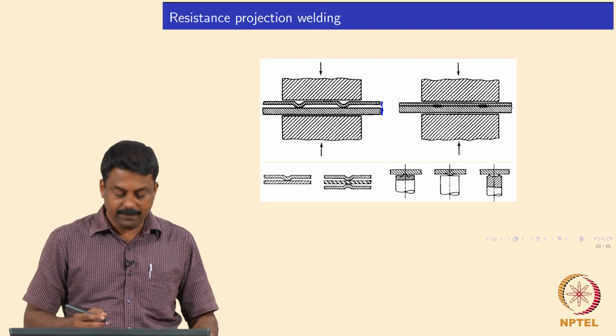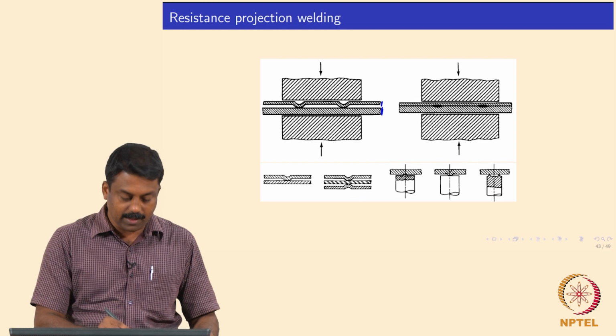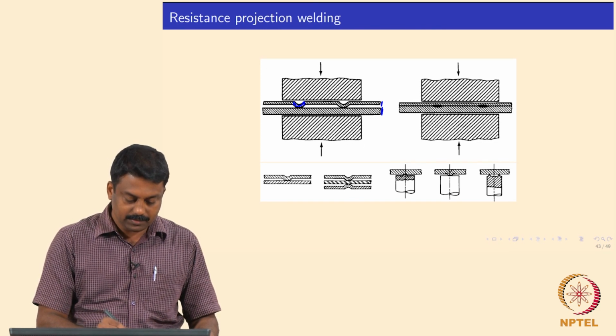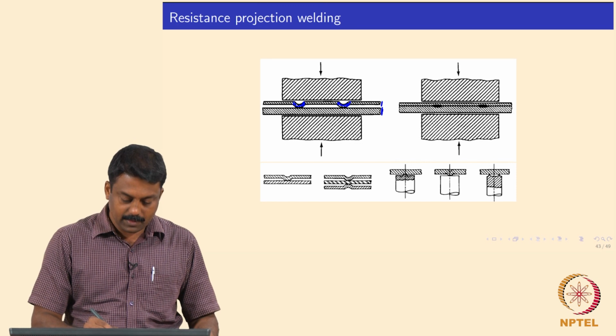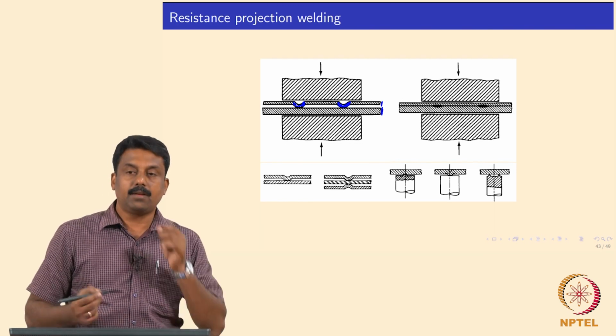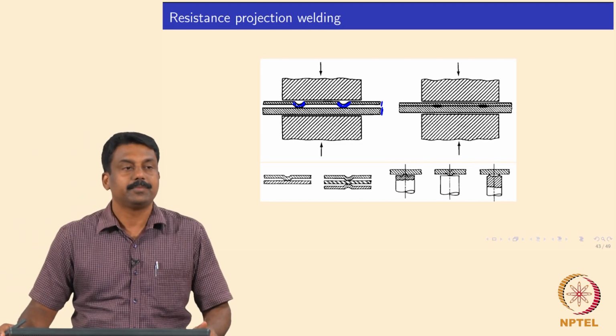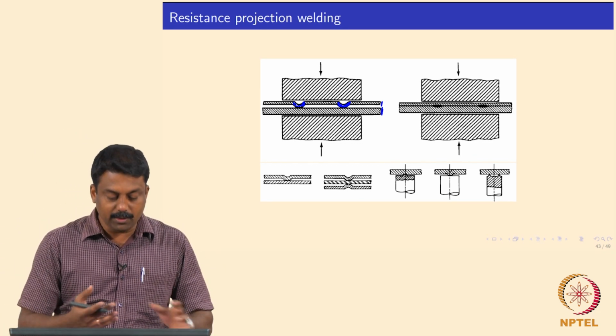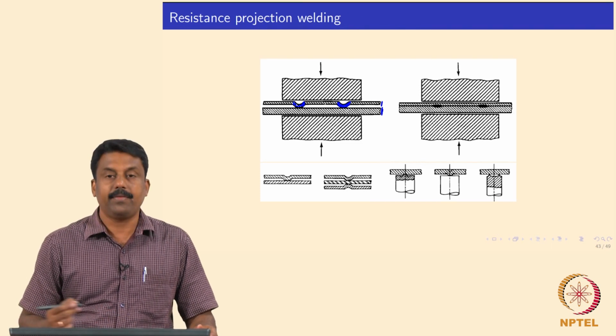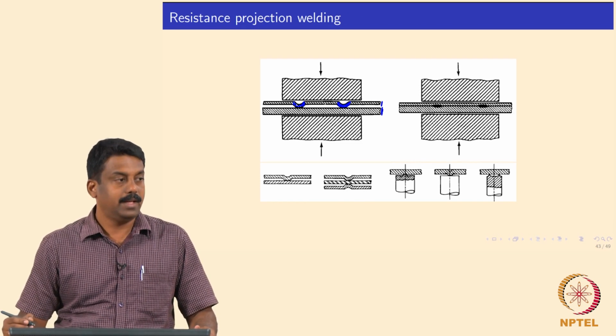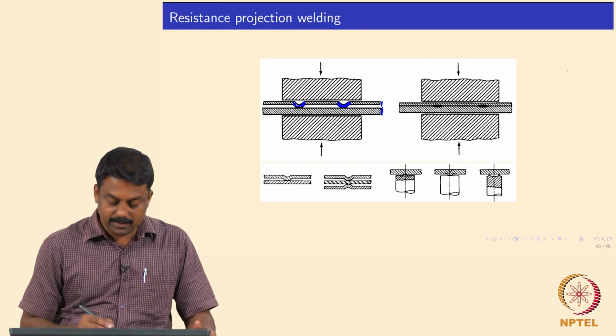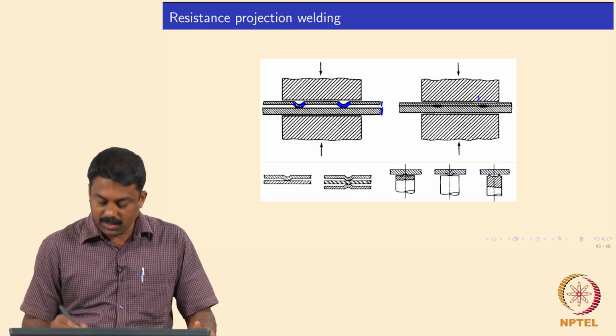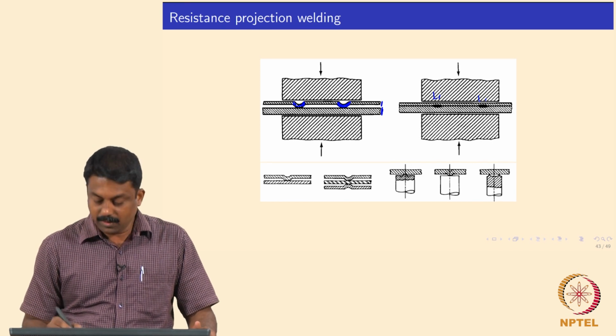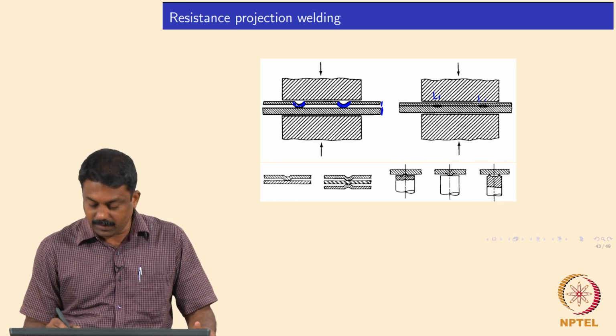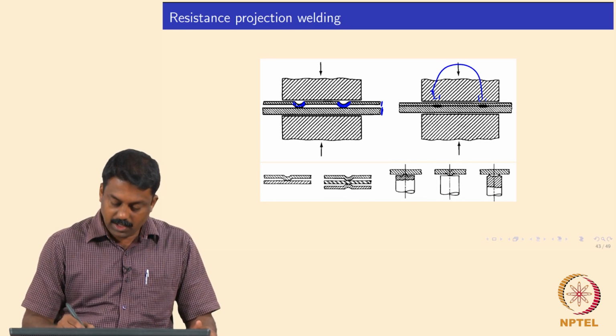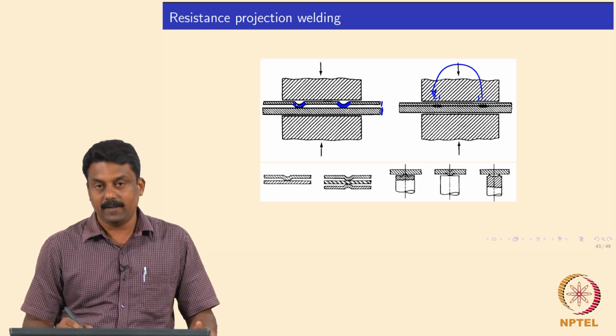So, instead of keeping two flat plates, you may also have projections in the thinner sheets. And because of that, the heat is concentrated, isn't it? You do not need a higher current to heat up the entire interface. If you are doing spot welding, individual spots, you need one electrode here and another electrode here. You first weld here and then go back with the machine to this point, and make another joint.